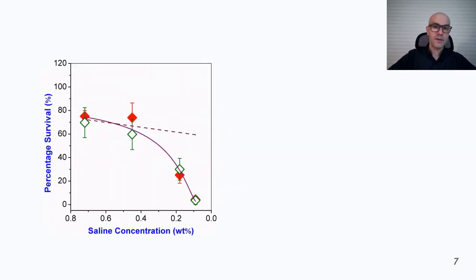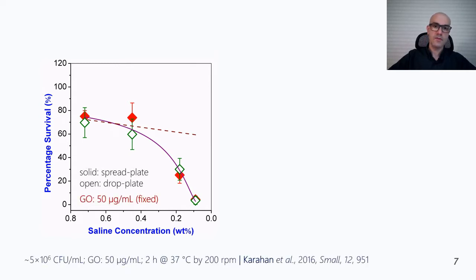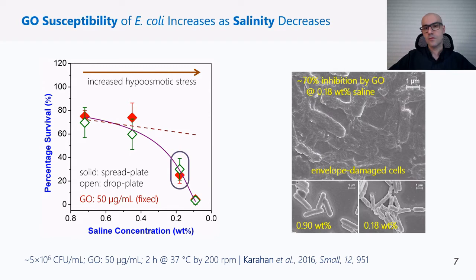And it worked as expected. In this graph on the left, you see the survival rate of bacterial cells as a function of the environmental salt concentration. Under the same graphene oxide concentration, as we reduce the salt concentration, the antibacterial activity increased markedly. Microscopy studies also provided similar observations and confirmed our hypothesis. So, graphene oxide shows higher antibacterial activity on envelope damaged cells by water shock effect.